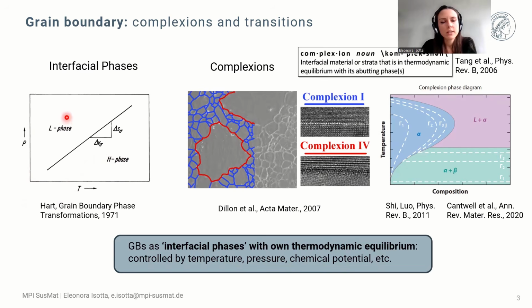Over the years, this has been proven and demonstrated, and especially after the 2000s, these types of studies have become more and more frequent. The terminology complexion has been established to refer to grain boundary phases, sometimes called defect phases. The grain boundary is really treated as an interfacial phase with its own thermodynamic equilibrium, controlled by thermodynamic parameters such as temperature, pressure, or chemical potential, i.e., the composition of the bulk material.